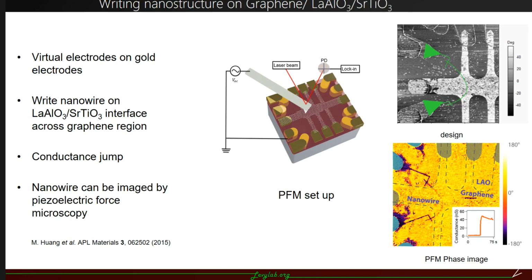So here comes the question: is the LAO/STO interface still writable with an AFM tip, even with graphene on top of it? Fortunately, the answer is yes. Here we apply positive voltage to the tip and write two funnels to connect these two electrodes, and we also draw one nanowire that goes across the graphene region. After the writing, we see a conductance jump between these two electrodes.